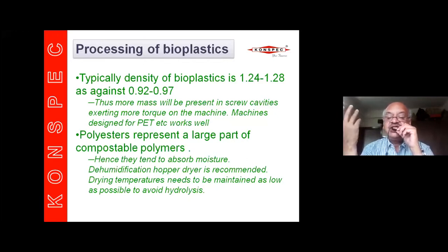temperature is in excess of 170 degrees, every molecule of water will break the bond and the molecular weight will fall down dramatically. So it is very important that bioplastics have to be dried to the extent of less than 50 ppm to make good products. Otherwise, there will be loss of property during processing. Secondly, at the hopper also, we ensure that the material is dried, and the material is dried at a least temperature, typically less than 50 degrees centigrade. Why? Because above 50, the hydrolysis rate will be very high.